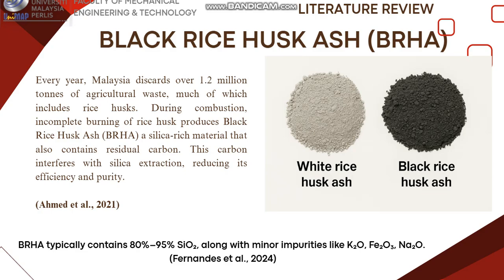The literature review of black rice husk ash. Malaysia generates over 1.2 million tons of agricultural waste annually, including rice husk. When burnt, rice husk produces black rice husk ash, which is rich in silica but contaminated with carbon. Studies show that BRHA can contain up to 80 to 90 percent silicon oxide, which makes it a promising source for sustainable silica recovery.